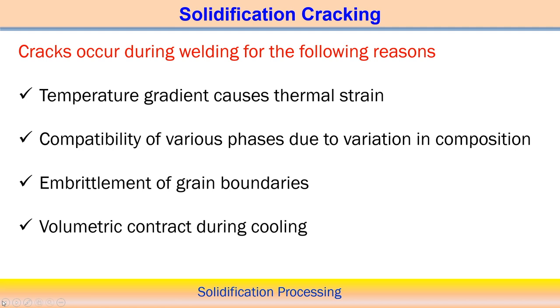There are 4 points I have mentioned here. One important parameter is the temperature gradient. Temperature gradient basically determines how much thermal strain is available. The thermal strain generated during the solidification process depends on the temperature gradient, which is the spatial difference of the temperature over a particular zone. So thermal strain can also be calculated.